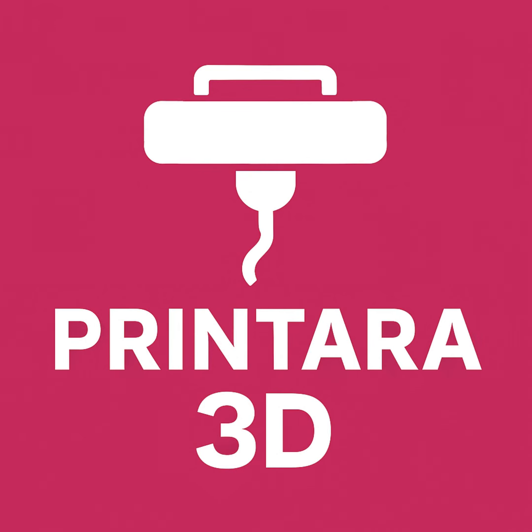It looks completely professional. And the source also points out that beyond just chemical smoothing, ABS is a dream material for traditional finishing work too. Like sanding. Yeah. If you try to aggressively sand PLA, the friction generates heat. Because PLA has that low glass transition temperature of 60 degrees Celsius, it starts to get gummy and melt right into your sandpaper. It ruins the part and clogs the sandpaper instantly. This is so frustrating. But ABS handles friction beautifully. It basically turns into a fine powder when you sand it.